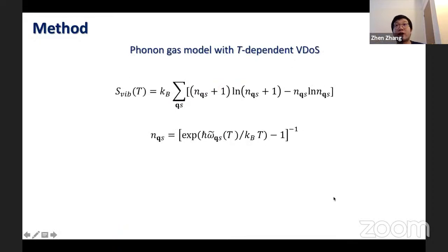By incorporating the temperature dependent vibrational density of states into the phonon gas model, we can then easily calculate the vibrational entropy, including anharmonic effects. In principle, anharmonicity to infinite orders in perturbation theory are captured in our phonon quasi-particle approach.